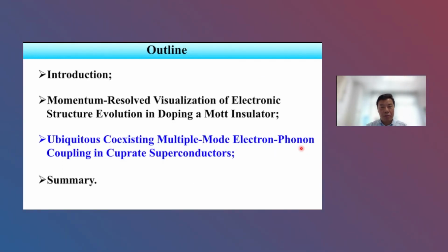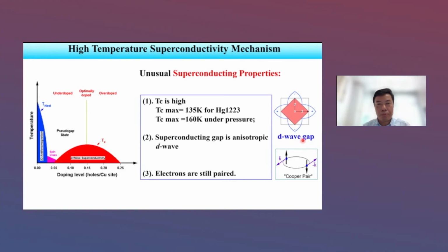Then I move on to the second topic of my talk today, the electron-phonon coupling in cuprate superconductors. And as we know, the high temperature cuprate superconductors exhibit some unusual superconducting properties. First, the TC is very high. Usually, the maximum TC now at ambient pressure is about 135 Kelvin for mercury 1223, and at high pressure can reach 160 Kelvin. The second most important part is that people already know that the superconducting gap is d-wave. It's not the usual s-wave as in other conventional superconductors.